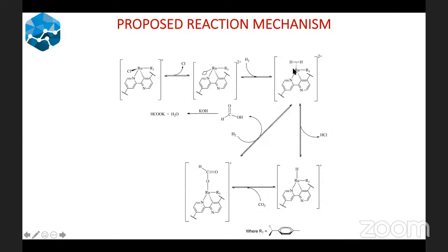then insertion of your hydrogen into the open metal site, you form that dihydrogen ruthenium complex, and of course the hydrogen also departs from that complex, and with concomitant elimination of your HCl, you then form the ruthenium hydride, which we believe is our active material, and then there is insertion of carbon dioxide to form this ruthenium formate complex, and of course it dissociates to give formic acid.